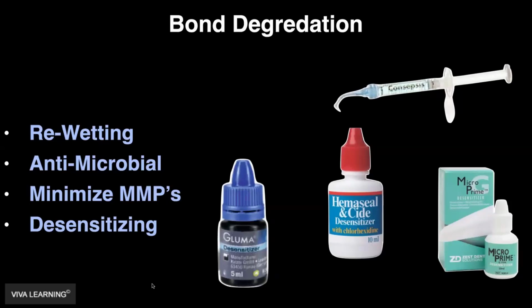One is 2% chlorhexidine, like in Consepsis. The other is 3 to 5% glutaraldehyde. And so those 2 chemistries basically are interchangeable. They both are antimicrobial, so they get rid of bacteria in the dentinal tubules that could cause a pulpitis. They both act as re-wetting agents. So if you have rinsed and dried, you can re-wet the dentin, which will improve your adhesive process. And most importantly, both 2% chlorhexidine and 3 to 5% glutaraldehyde minimize the production of MMPs, thereby slowing the process of bond degradation to dentin.